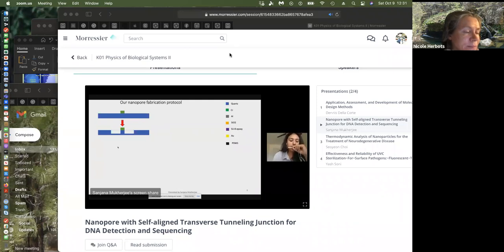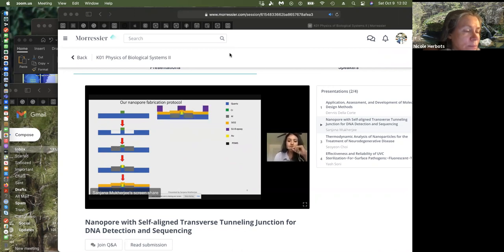The DNAs will be lodged and will be driven to the other side. We deposit aluminum metal on the trenches. Then we lay out our electrode, which we are seeing at the cross-section view. So you can see the electrodes are actually going into the screen. Then we lay our dielectric, silicon dioxide, 100 nanometers of that.